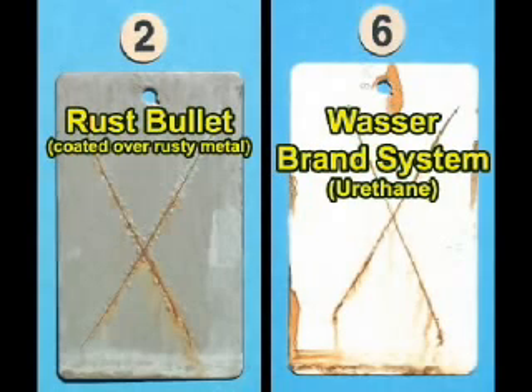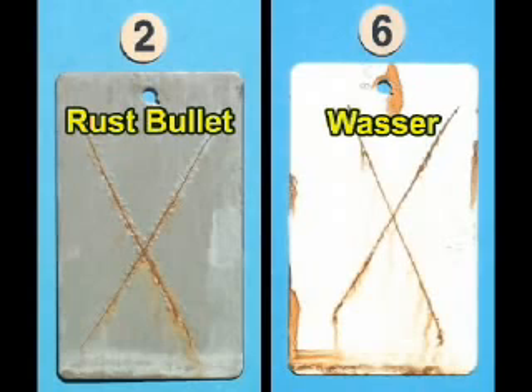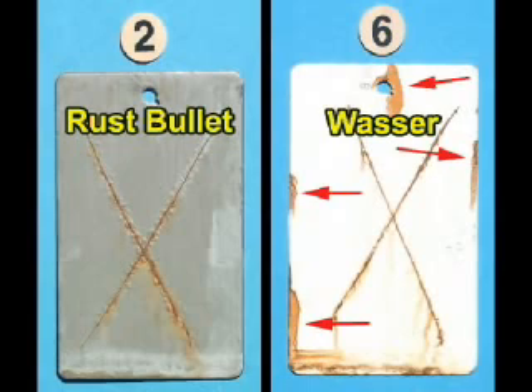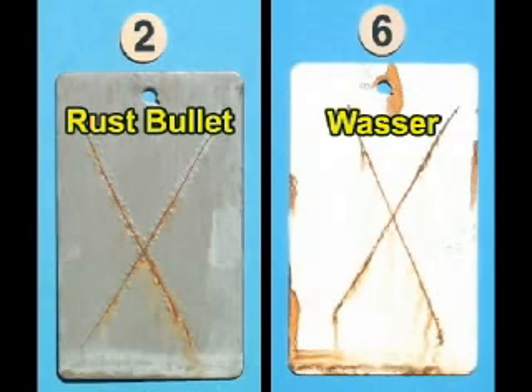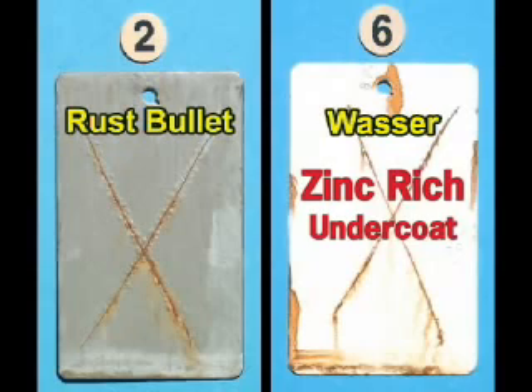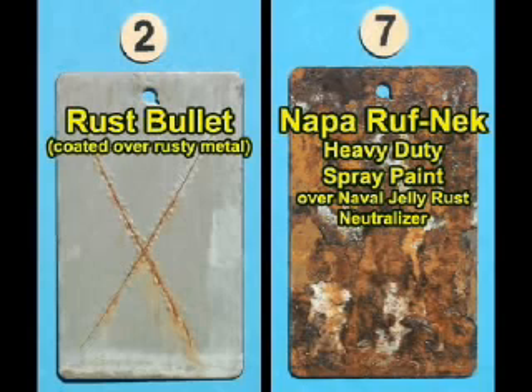This panel is coated with the Wasser brand system. This is the second best test panel in the series and represents the peak of old technology. A significant rusting and undercutting is taking place at the hole and the edges, which indicates the difficulty of the system in covering sharp edges and corners. The scribe line is undercutting as well. Like the test panel number 5 with Rust-Oleum cold galvanizing compound, the three-step Wasser process utilizes a zinc-rich undercoat that provides a degree of galvanic protection which allows the Wasser system to do as well as it has done. But the use of a zinc metal undercoat brings along with it most of the problems of a zinc-rich primer system.